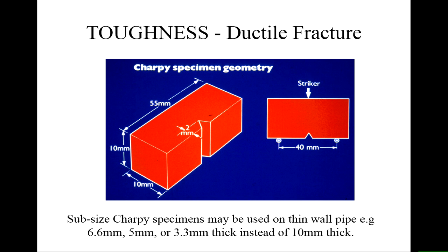So standard workshop equipment can be used to make these samples. In the Charpy test, there's a support which is 40 millimetres apart, and a swinging pendulum comes and hits the back of the sample to provide the energy. What normally happens is you lift it up to a certain height, there's a certain stored potential energy, you swing it down with no sample in the way, and you see how far it goes up, and that's the losses just from the bearings in the machine, and you can set that. Then when you put the sample in the way and it breaks, some of that potential energy is absorbed in breaking the sample, so it doesn't swing up quite so high. By seeing how far it swings, you can work out how much energy has been absorbed by the sample. It's a very, very simple test.